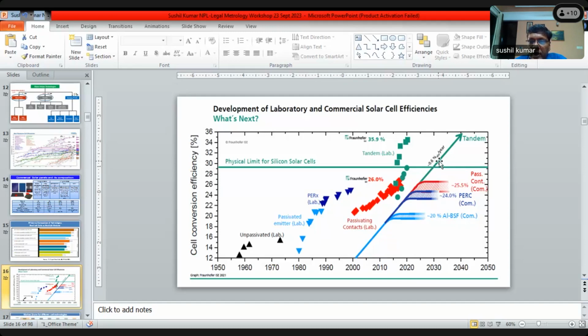Now people have started working on the tandem solar cell, though it is not in the market, but at lab scale it is presented. And this line is about 29%. It is the physical limit for silicon solar cell, the 29%. With a single cell, it is not possible to go beyond that. So people have started using some other material along with the silicon, one cell over another cell, the stack of cells, so that efficiency can be improved. So starting from aluminum BSF, the back surface field, to today's technology, the PERC, that is passivated emitter rear contact cells, this is how the progress has been made.